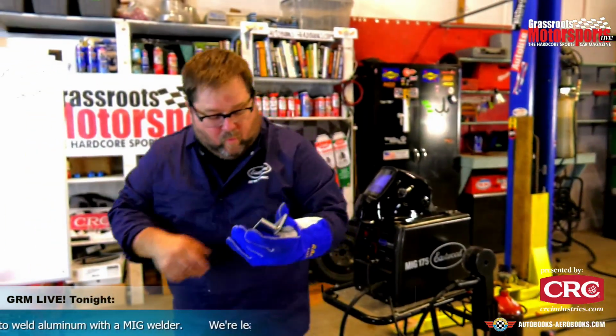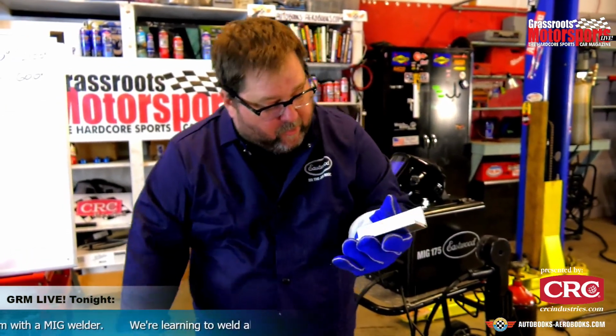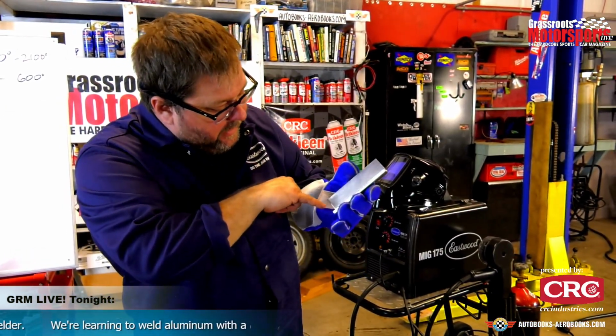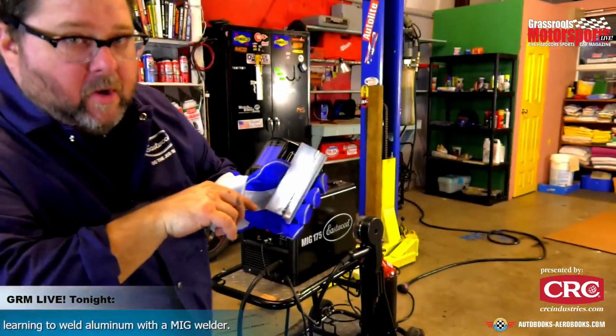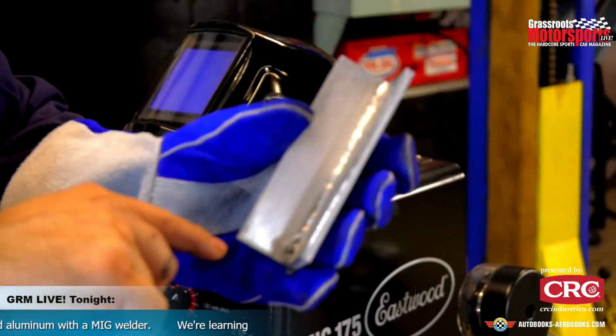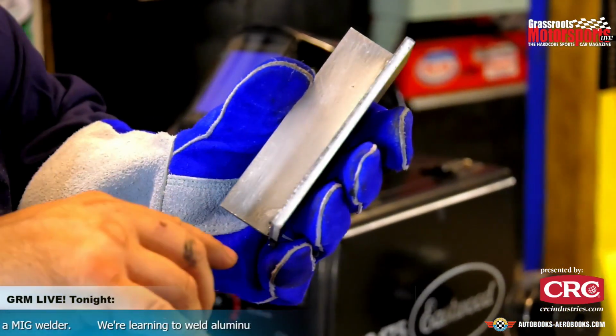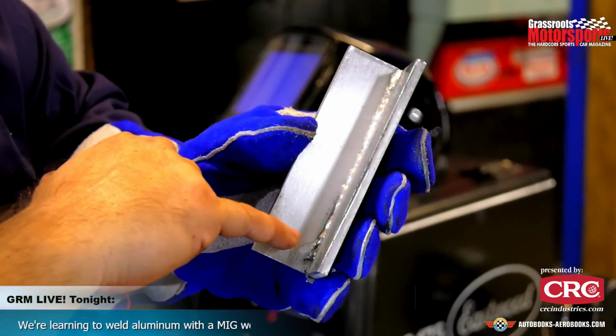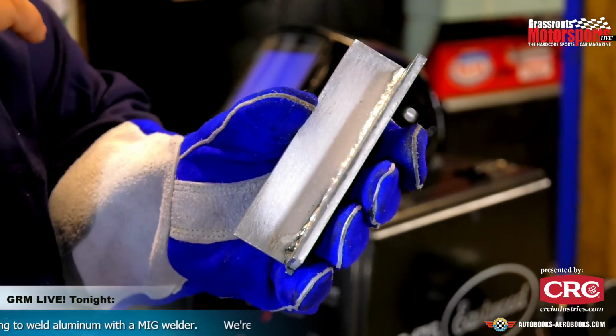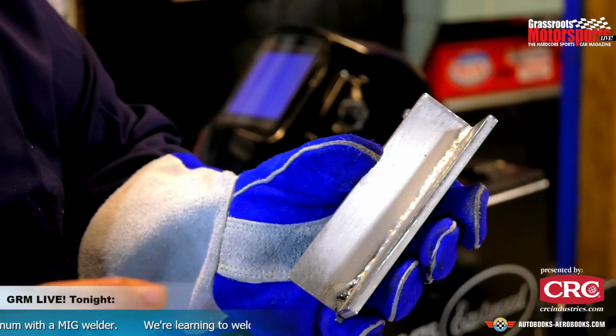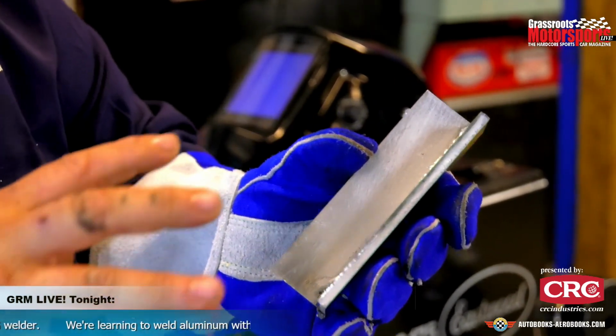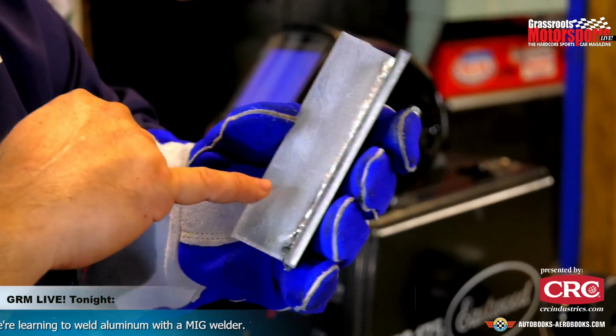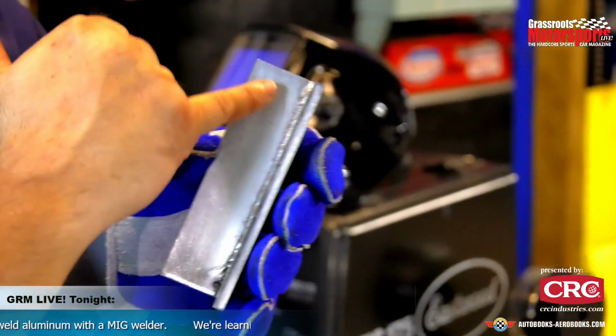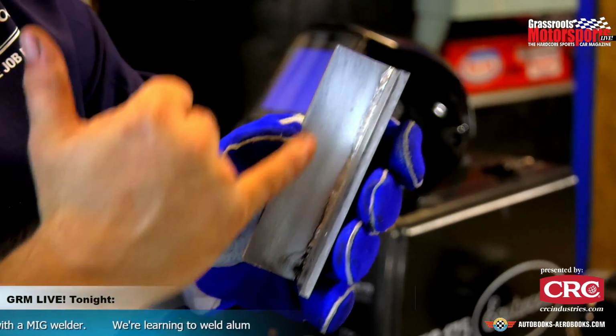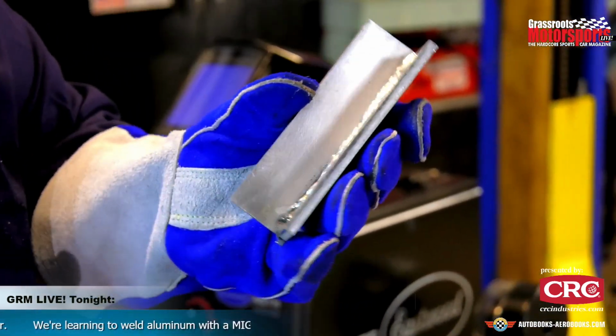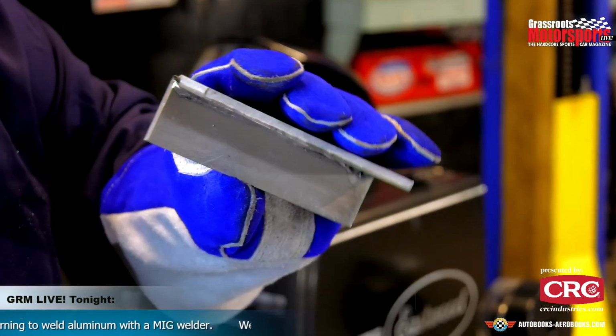All right, so what can we learn from this bead? We can see that at the start we had some spattering, we had some incomplete penetration, and we had a little bit of mounding here. The mounding is more than likely going a little bit too slow, or not quite having enough heat. Here, as I started to accelerate through the weld, we actually have a nice bead going through there, and pretty good coverage.